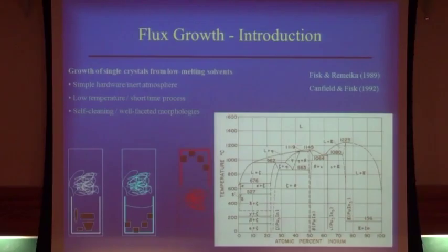And then you go to a temperature where not necessarily your atoms are melted, but your flux is melted. And then you choose the right concentration and temperature profile to provide the nucleation of the phase you are looking for. And then you cool very slowly and stop at a certain temperature where you already have your phase, but you can expel the flux. You can use a centrifuge and get your flux out and keep the crystals.